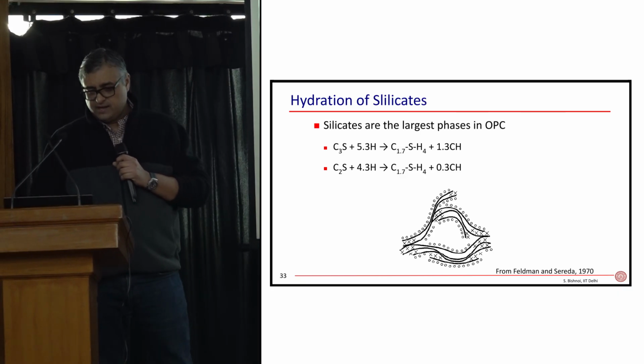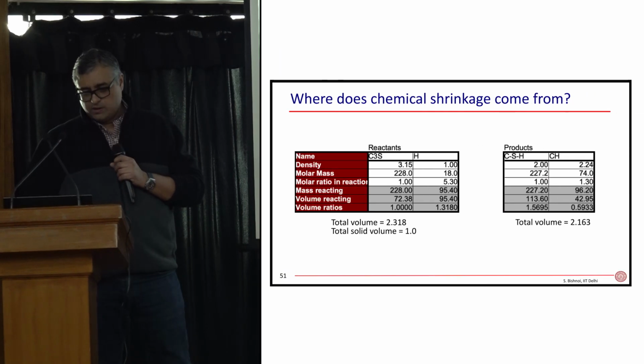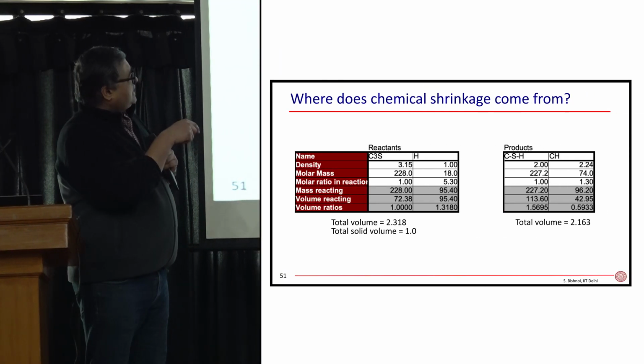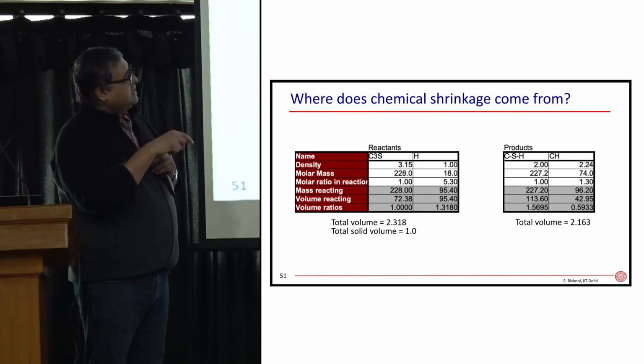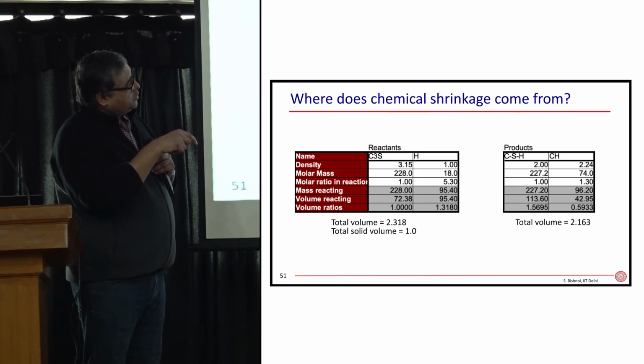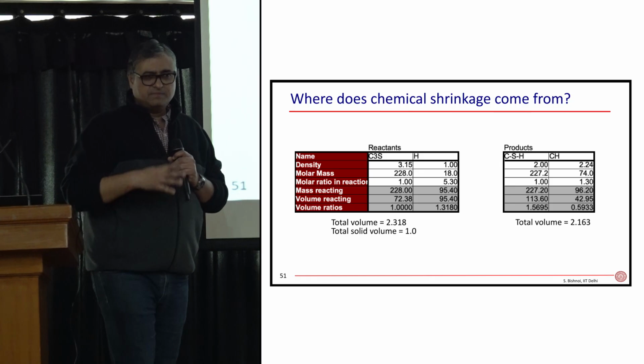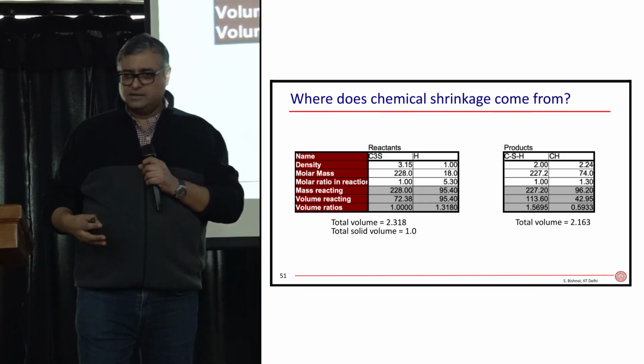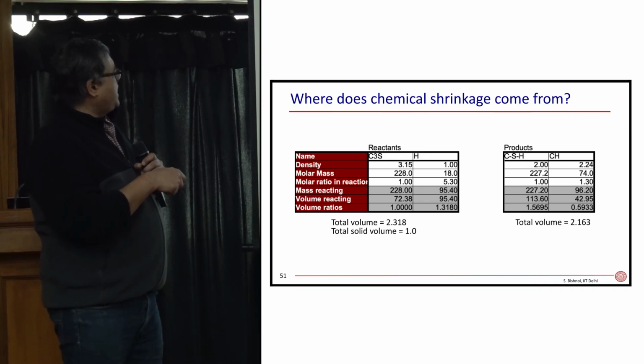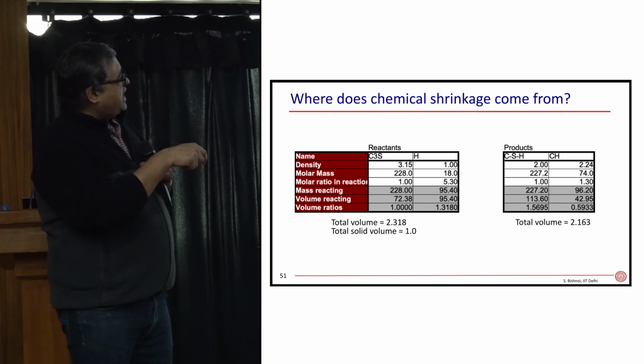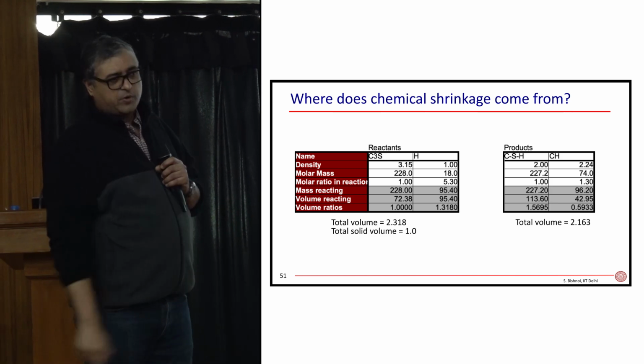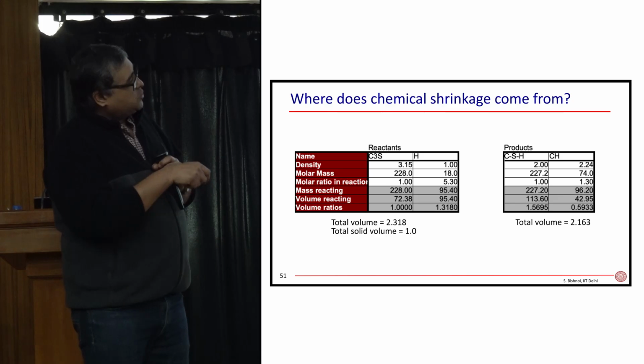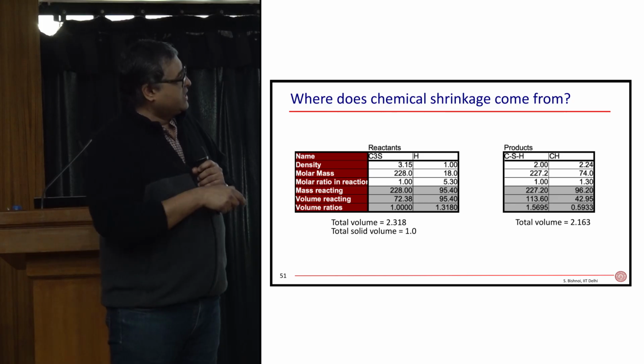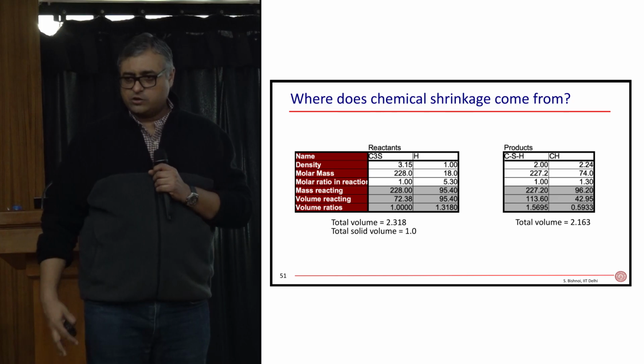So let's come back over there. We have these numbers 5.3 and 1.3 over here, and now I calculate what is the mass that is reacting. So I multiply this number by that number, 228 grams. Using the mole concept: 228 grams of C3S reacts with 95.4 grams of water to produce 227.2 grams of CSH and 96.2 grams of calcium hydroxide.